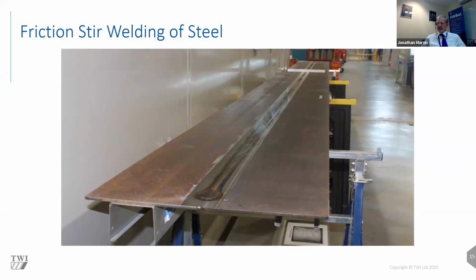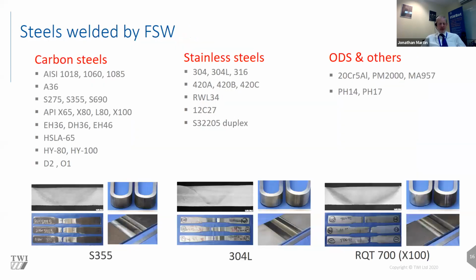And I think this picture on the screen here quite clearly shows one of the major benefits of friction stir welding. This is a 6 meter long steel panel that has been friction stir welded. So friction stir welding is a low distortion joining technique. Since that time, TWI, along with other practitioners of friction stir welding and research organizations, have been looking at joining steel. I don't think we've come across a steel that we can't join, ranging from carbon steels, construction steels, pipeline steels, steels used in shipbuilding, etc., along to the high carbon D2 content steels. A range of stainless steels, the austenitic 304, 316, through to the martensitic and duplex. And also we've welded some of the very difficult to weld steels, such as the precipitation hardened steels and the ODS, which are impossible to fusion weld.